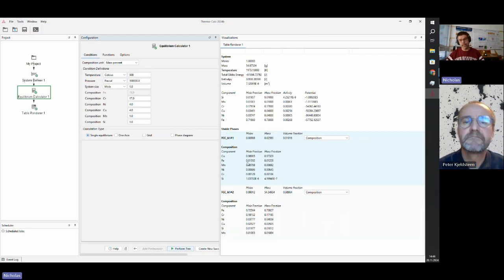And this is again known, right? There is a miscibility gap between the iron-rich side and copper. So it's known that if you cool down, you basically get a demixing of copper, like in a salad dressing. If you have oil and vinegar, you've got little copper droplets that nucleate out of the FCC. But it's also FCC, right? It's FCC precipitates in an FCC matrix.